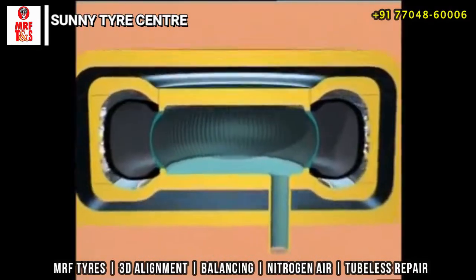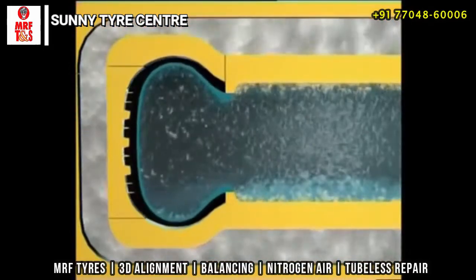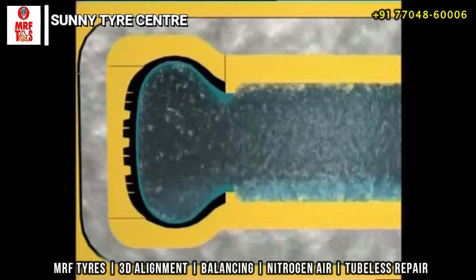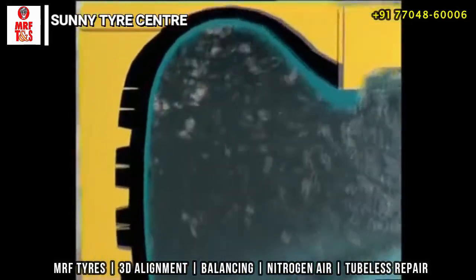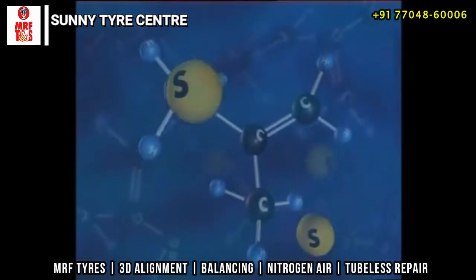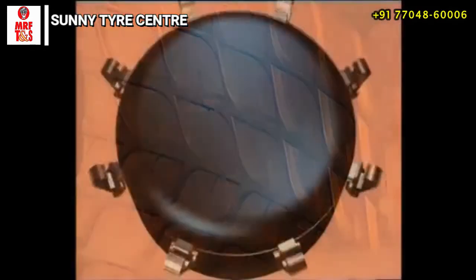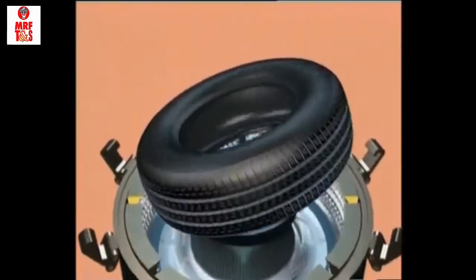In the center, a bladder filled with pressurized hot water pushes the still malleable material to the base of the patterns engraved in the mold. The heat of the water and steam surrounding the mold will cause curing to begin. The rise in temperature causes vulcanization of the rubber. The sulfur incorporated into the rubber compounds forms bonds between the polymer chains. At this point, the rubber switches from a plastic state to an elastic state. When removed from the mold, the tyre has acquired its definitive form and properties.